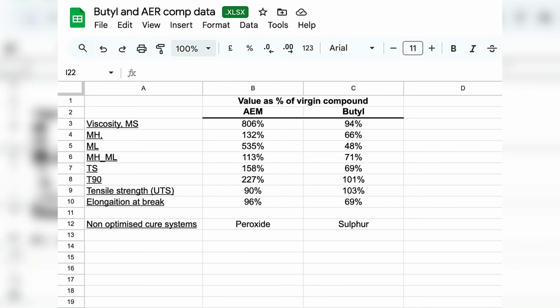The data is normalized as a percentage of the original values. For the AEM compound, the MDR data shows a higher minimum torque, indicating increased viscosity after decrosslinking. This aligns with what you'd expect from some loss of plasticizing components during the original vulcanization, which weren't fully replaced.